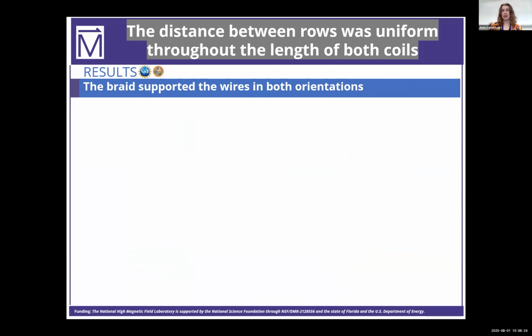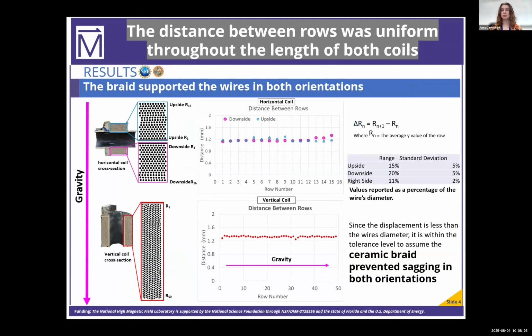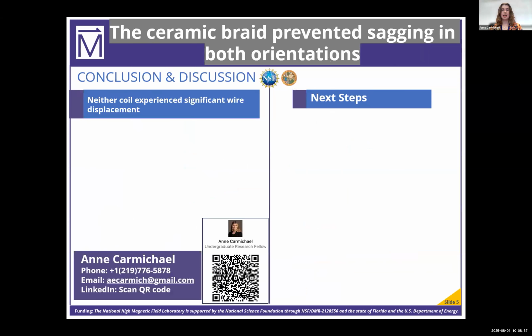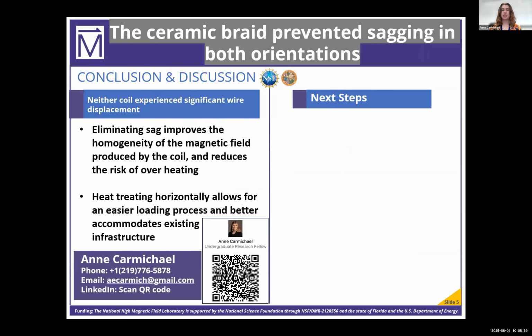When both of these coils were analyzed, it was found that the distance between the rows of wires was uniform for both the horizontally and the vertically heat-treated coil, indicating that the braid was able to successfully keep this sagging from occurring. Since this sagging did not occur, the homogeneity of the magnetic field was significantly improved, and it also reduced the risk of the coil overheating.